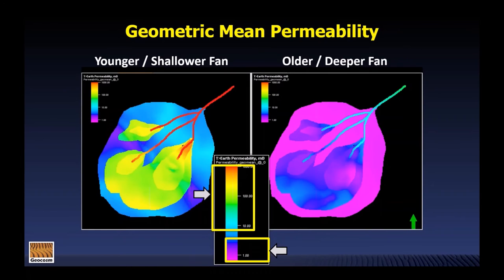So here is our predicted geometric mean permeability for these two fans. And as you might expect, by looking at those differences in intergranular porosity through time, what we see is that in the deeper fan, where we have a greater extent of diagenetic alteration, the range in the geometric mean permeabilities between the channel and the outer lobe are pretty small. On the other hand, if we looked at that equivalent position here in the shallower fan, we're seeing over two orders of magnitude difference in the geometric mean permeability.